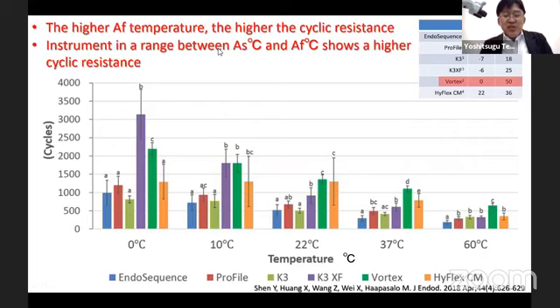And this study shows, Shen has many studies, and she showed the higher AF temperature, AF means austenite finish temperature, the higher the cyclic resistance. An instrument in the range between austenite start temperature and austenite finish temperature shows a higher cyclic resistance.